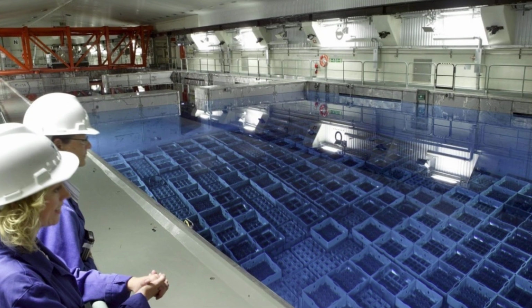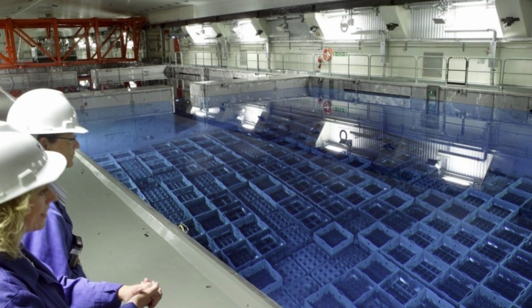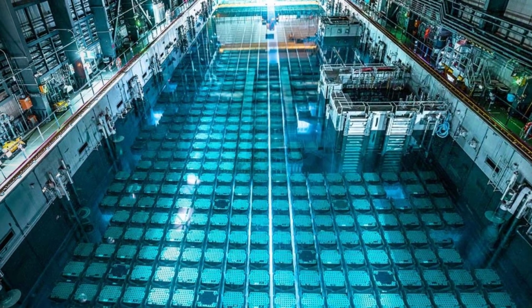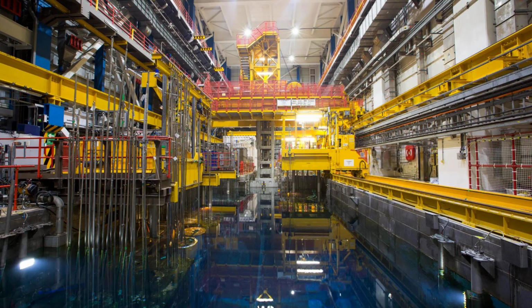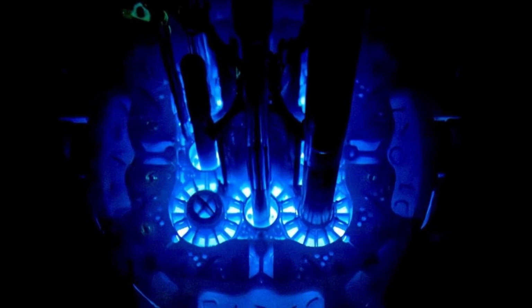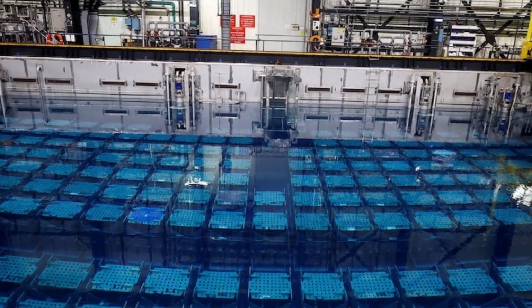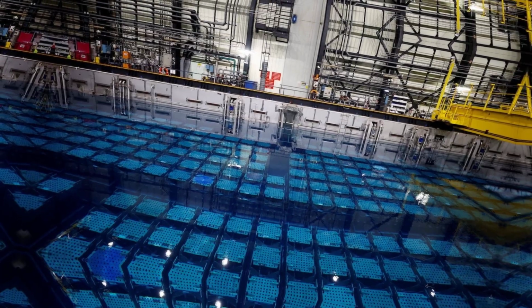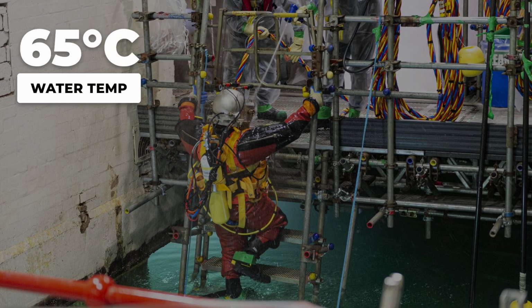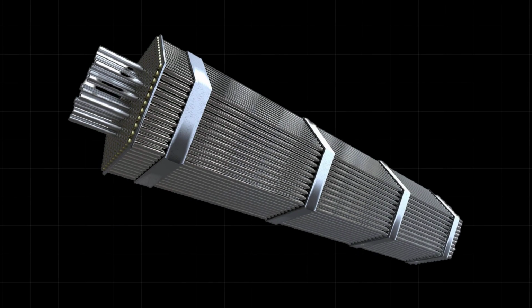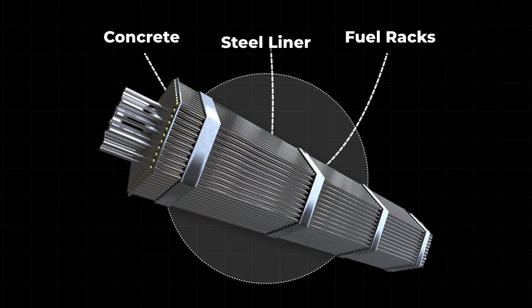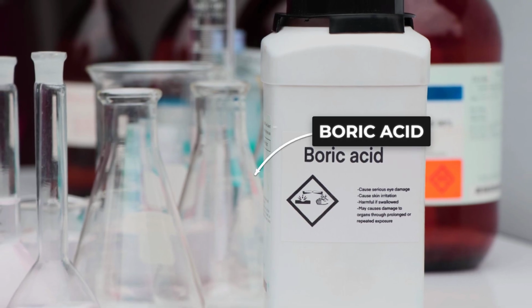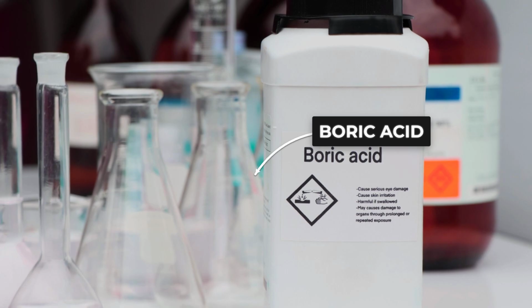The answer engineers have settled on is a process that takes the waste through a series of stages, each one designed to handle the fuel at a specific level of intensity. The pool is stage 1. It exists because the fuel coming out of the reactor is too hot, both thermally and radiologically, for any other form of storage to work. Inside a typical spent fuel pool, water temperature is held below 65 degrees Celsius by the cooling system. The pool itself is reinforced concrete several feet thick, lined with welded stainless steel to prevent leaks. The water is treated with boric acid, because boron is one of the most effective neutron absorbers known.